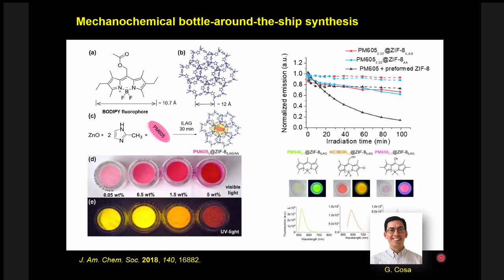For example, with my colleague here, Gonzalo Cosa, who is an expert in luminescence spectroscopy, we actually have shown we can use this methodology not only to make these MOFs by grinding things together, but if you add in a small amount of a fluorescent dye, these boron dipyrromethenes, BODIPYs, you can actually trap this dye inside this framework as it's forming. And now you have this new generation, if you wish, of fluorescent materials. And it turns out you can actually put different dyes in there. So you have red and green and blue. And now we are looking at how do we actually get white light out of this. So a really fun collaboration, very colorful, but again, it shows how you can generate new, more complex systems through mechanochemistry.